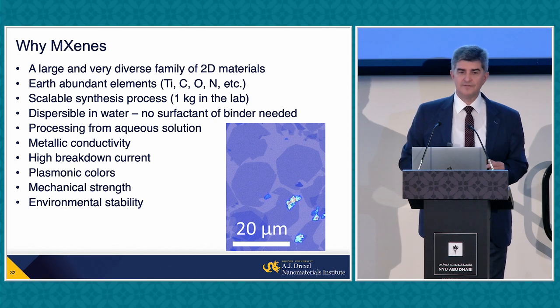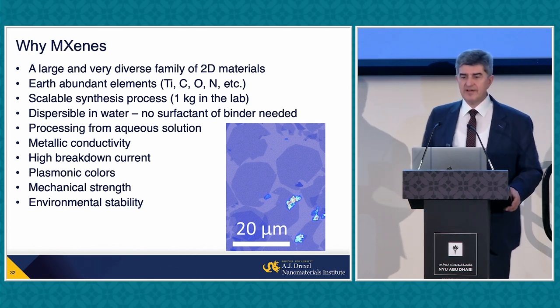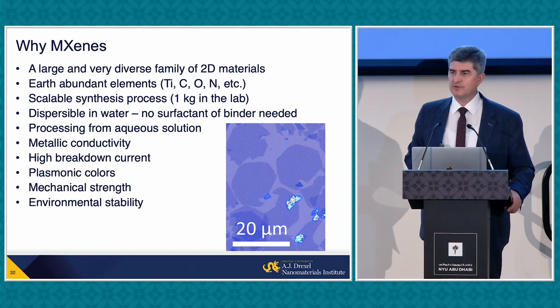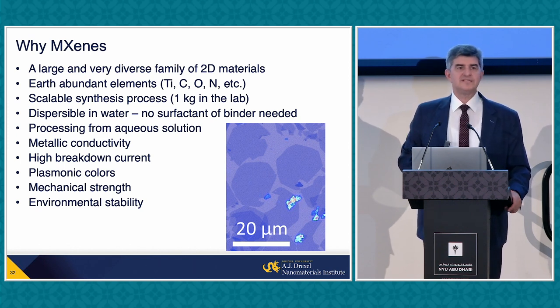It's also interesting. I can tell you right away, these flakes are very strong, even though you see some cracks and breakage, because I doubt that anyone has ever seen a solution-processed monolayer that is sub-nanometer in thickness. Graphene oxide is the only one you can actually see. Any metal chalcogenide, any oxide, which have been studied by thousands of people for decades, I've never seen a solution-processed flake larger than maybe 1-2 micrometers. They simply break because they're not mechanically strong enough. You can do it here. So at the moment, we'll explore it here.